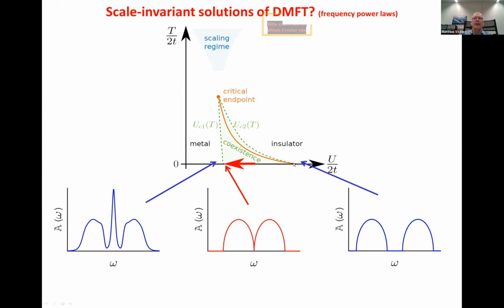This is the other side of the coexistence regime. This is UC2. And at this point, the middle peak disappears, in a way that the weight of this quasi-particle continuously goes to zero. Which means if I'm here in the middle of the coexistence regime, there are really two phases, and you can actually see this in experiments also as two domains of an actual sample.